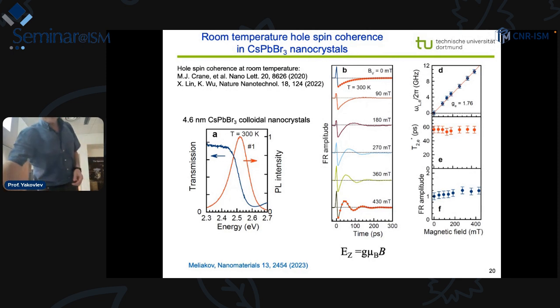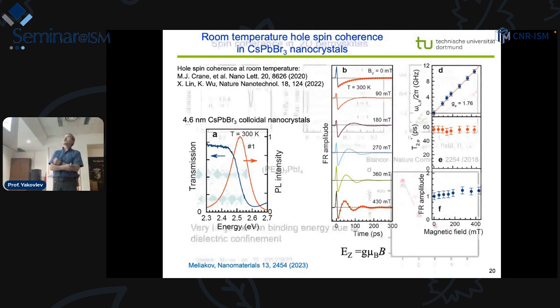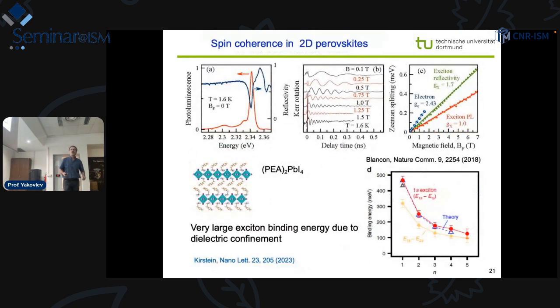One can also apply these techniques for the two-dimensional materials. I show only one example here. This is the lead iodide, where a single layer of the octahedra of the perovskites is implemented, and these layers are not electronically coupled with each other. The exciton binding energy in these materials goes up to 500 millielectron volts. So the materials became very much comparable with the transition metal dichalcogenides, the materials which many teams have started with.